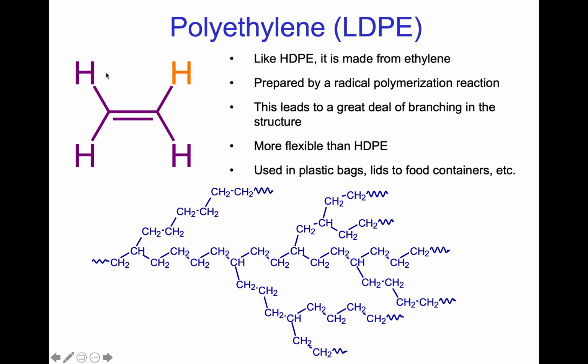Low-density polyethylene is the same monomer but radical polymerization, so you get that branching because you start getting those hydrogen abstraction reactions, and then you have radicals in more than one place on the chain, and they can elongate from both of those new radicals. Plastic bags are low-density polyethylene, so all of your shopping bags that you get. And then often the lids to a food container are low-density polyethylene, whereas the container itself is high-density polyethylene, because you want more flexibility in the lid since you're taking that on and off. Although now you'll see that a lot of lids to food containers are in fact polypropylene, which is number 5.